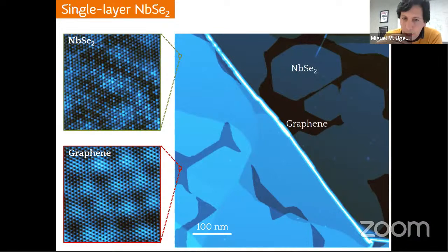These are tunnel microscopy images where you can see that we can work with coverages at our will, but we usually work with coverages slightly below 1 monolayer because we're interested in having the graphene substrate as a reference. In general, the typical size of our domains is around 400-500 nanometers, as you see here. Here I show you another atomically resolved STM image where you can see the emergence of the 3x3 charge density wave. But again, we can also complete the monolayer of niobium diselenide if we need to.